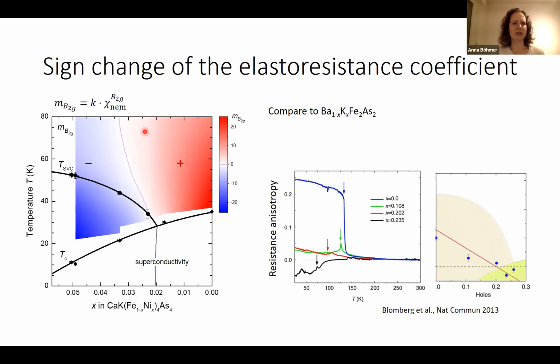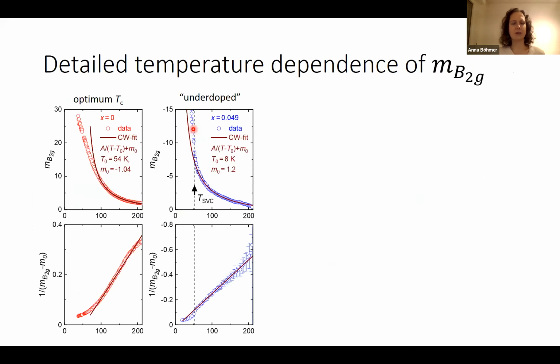So what we also see is that in vicinity to sign change, the temperature dependence becomes rich. So there's a sign change as a function of temperature as well, and that must also be related to this prefactor. But we think that maybe if we go far enough away from that sign change, we can learn something about the temperature dependence of the nematic susceptibility from the temperature dependence of the elastoresistance on these extreme compositions. And that's what I've shown here.